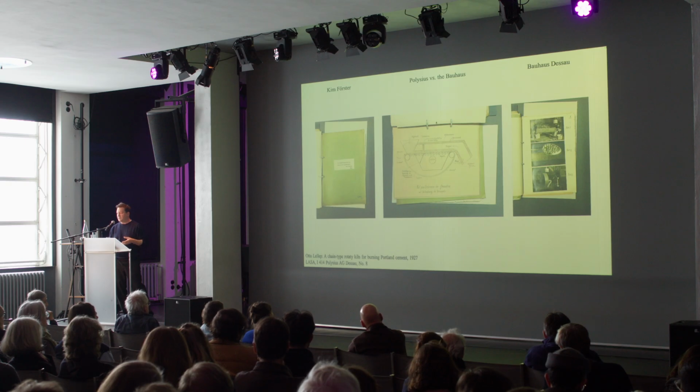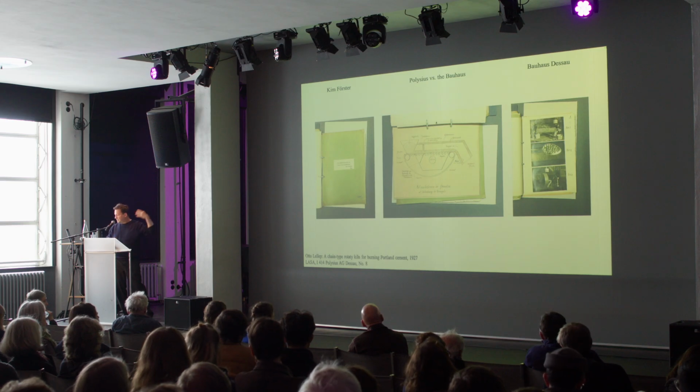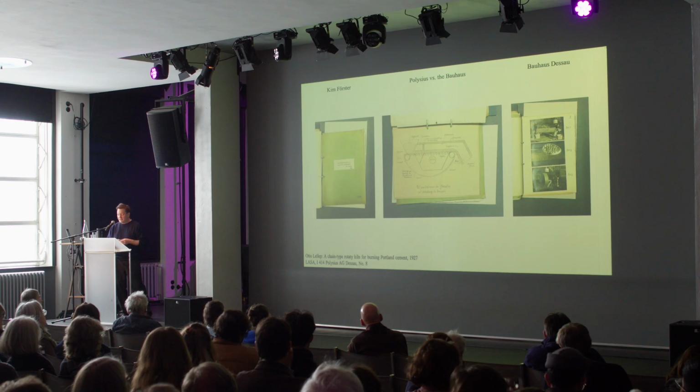A major breakthrough came through collaboration with engineer Otto Lellep to optimize firing processes. In 1927, Polysius patented the Lepol kiln, which is to be traced in the state archives to a combination of Lellep and Polysius, and an innovative technology processing raw materials not as slurry, but as granules or pellets preheated on a traveling grate and applied at an industrial scale. Recovering waste heat actually reduced fuel consumption significantly, by more than a third.